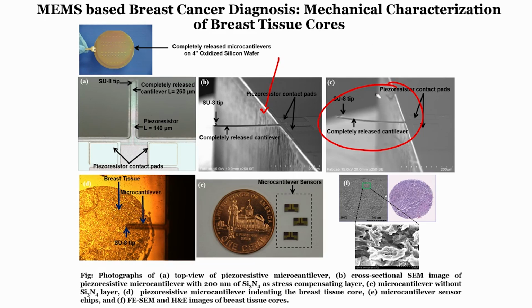So there is a compression in the cantilever. This compression can be taken care of if I use silicon nitride. In this case I deliberately have not used silicon nitride, and that is why you can see the cantilever is having more stress because of the silicon dioxide. But in this case I have used silicon nitride as well as silicon dioxide, and that is why the stress is being countered by the silicon nitride. Now, there is an SU-8 tip, and this is the back side, so this side is here on the top and the SU-8 is touching this tissue. This is a breast tissue slice, and this is how the individual chips look.